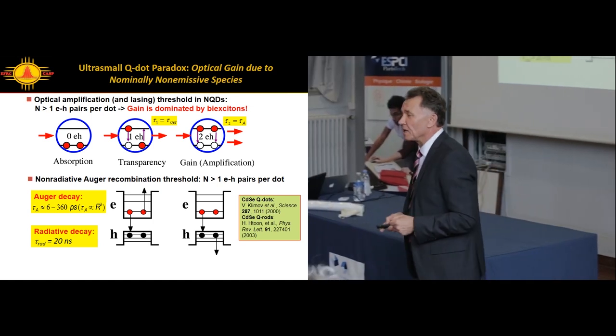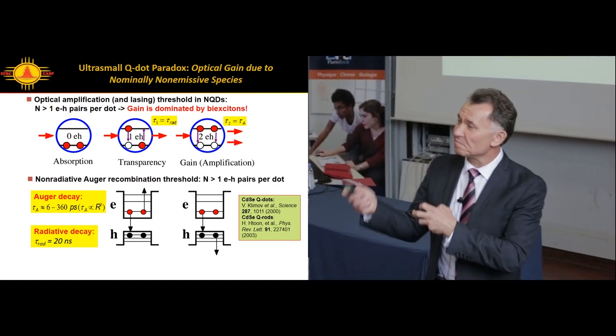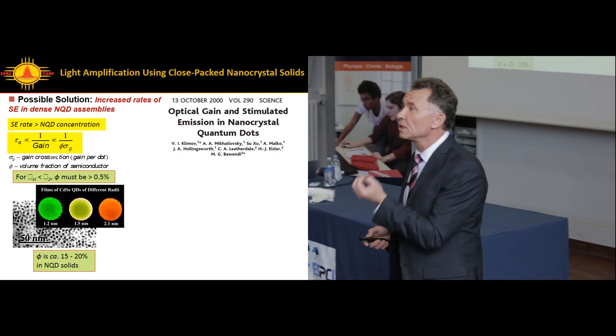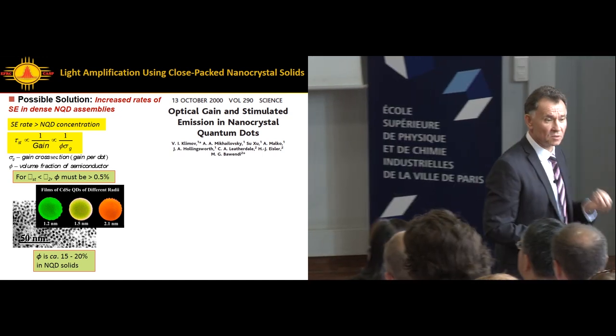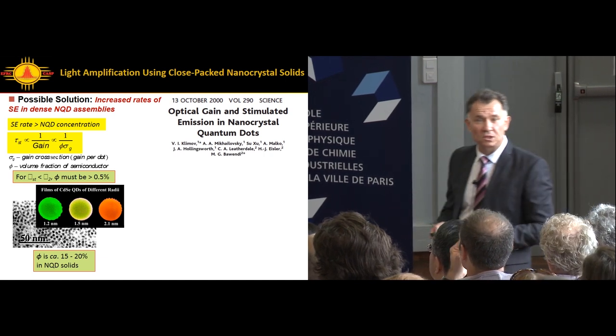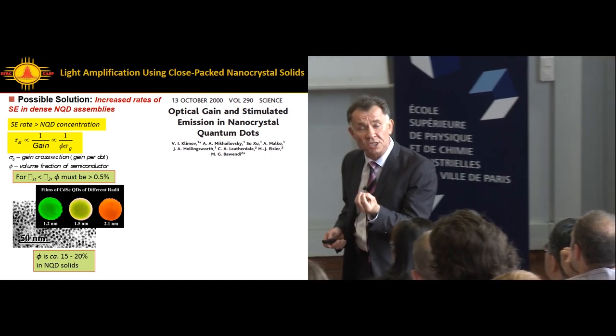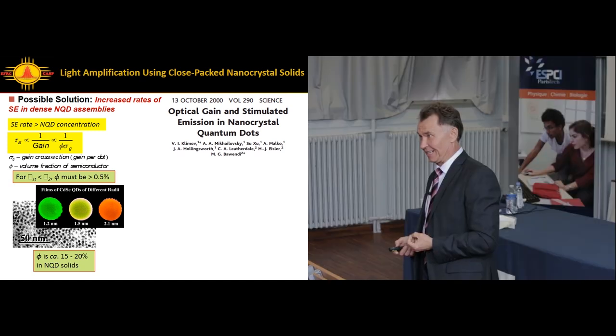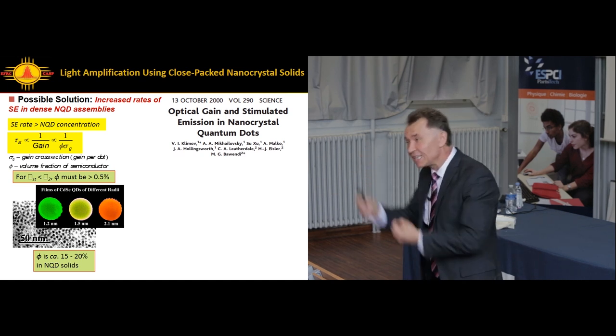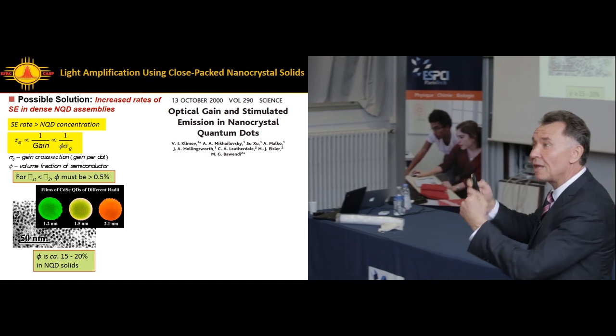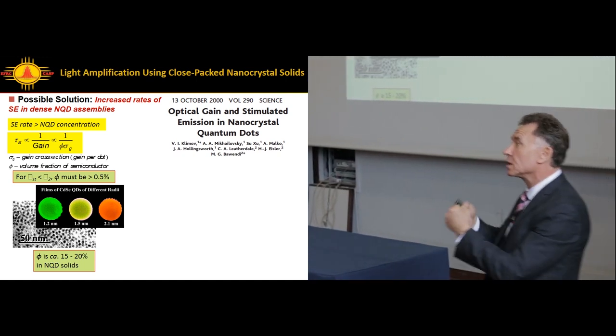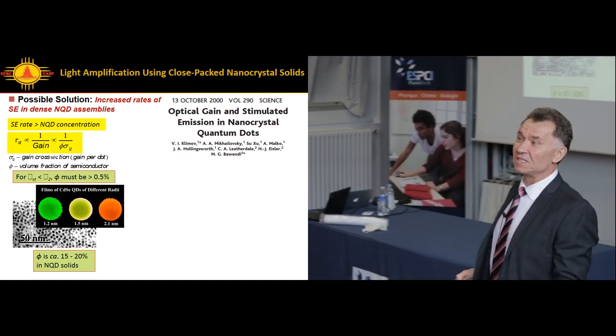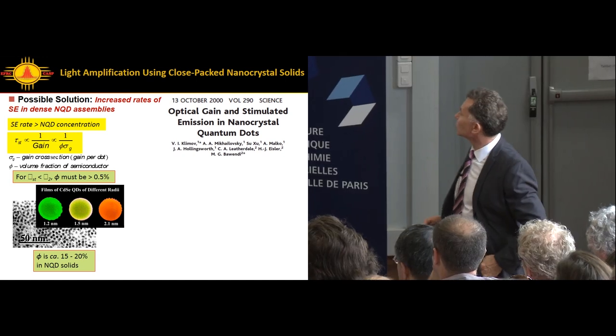What was the solution? Luckily, I graduated from the physics department specializing in lasing. We knew in order to resolve this problem, we need to look at the development time of stimulated emission, not spontaneous, and the lifetime of stimulated emission. In addition to the dipole moment of your transition, linked directly to the density of your emitters. It's a collective effect. One dot stimulates the other. Increasing the packing density can build up the gain such that the growth time of stimulated emission becomes shorter than Auger recombination. That was the simple secret.